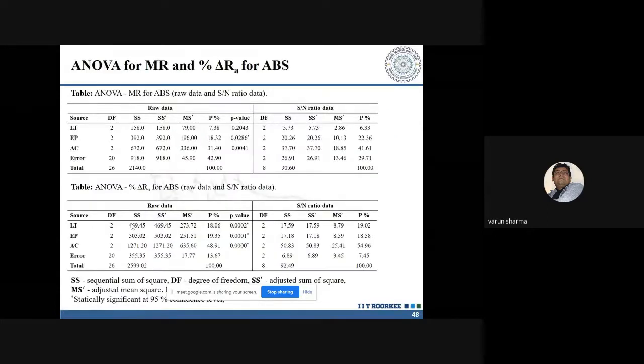Similarly, for the case of the extrusion pressure and the abrasive concentration, it resulted in a better smooth surface for the ABS as well as the PLA. We did an analysis of variance and found that the extrusion pressure was the most significant parameter when you took ABS into consideration. For material removal and for Ra, different parameters contributed. Fine. Now, this was the work that contradicted the initial findings.